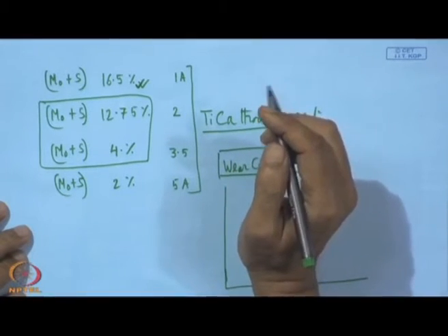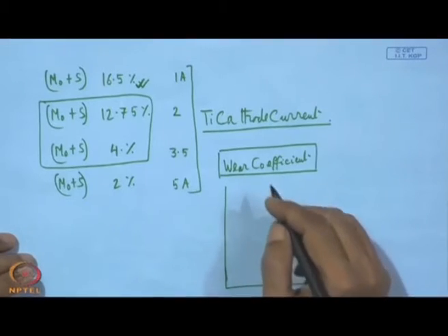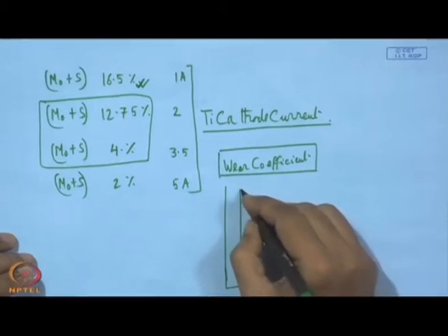and this is just a balance between Ti cathode current and that of MoS content, and at the same time the coefficient of friction can also be obtained with a rather favorable value. So, this is on one side the coefficient of friction, and on the other side the wear coefficient. Now, considering these two, we find that the wear coefficient will be quite high on this side.